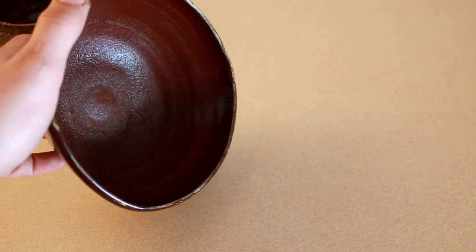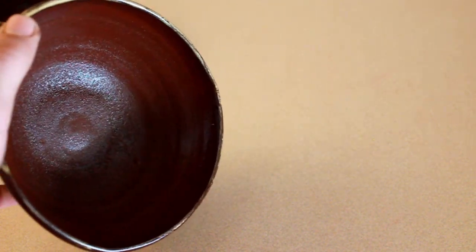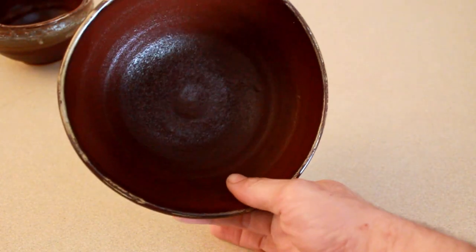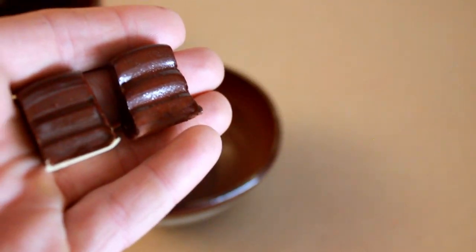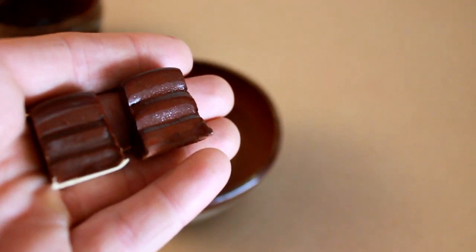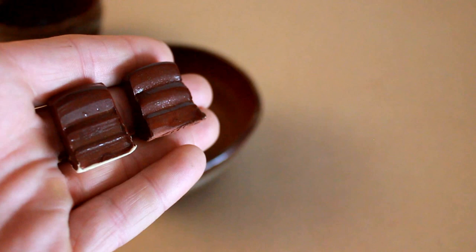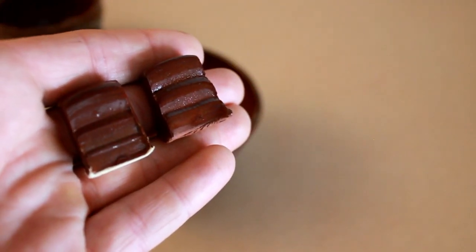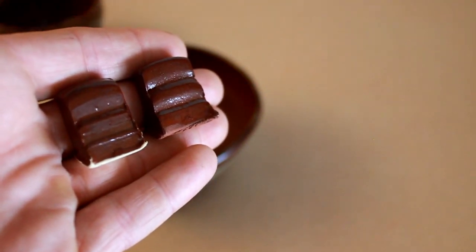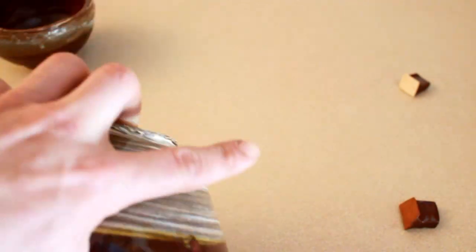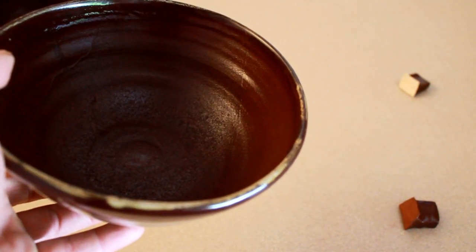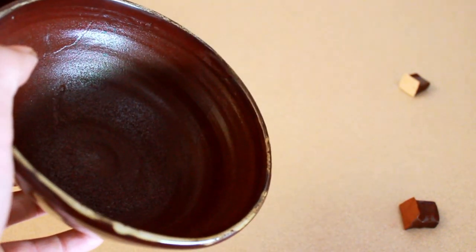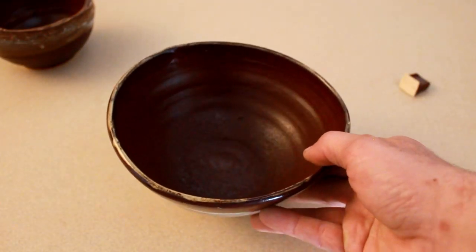Boom! This is why it's on the bottom slot. This thing is crater central. This thing looks like a 13 year old going through puberty. It's full of craters and it's ugly. This is one of the main reasons why I always test my stuff on actual bowls and products before I put them out. Most potters will test their glaze on test tiles just like these. These are the same exact glaze, these two right here. And they'll put them on these test tiles to see if they're viable or good before they test them on a real product, like this bowl right here! But I've learned over time not to trust these. These right here just look like a darker brown, look kind of burgundy reddish, but they're really not. But usually what would happen is you would get something out of the kiln like this and you would go, oh, okay, so it's not a brilliant glaze, but it still works. And then you'd make a big old five gallon batch of it and be like, eh, it'll do. No, no it won't do. This is seriously like one of the reasons that I always test my stuff on test tiles and bowls. It's simply because they come out massively different on a real product sometimes than they do on a testile. So usually I'll make a crappy bowl and I'll make some crappy test tiles. But I am going to reglaze you because of your backside, beautiful girl.